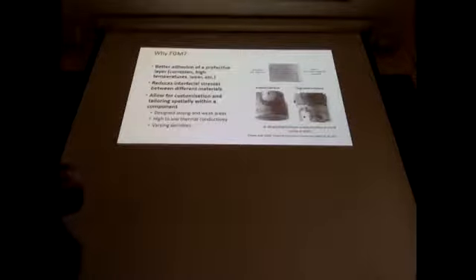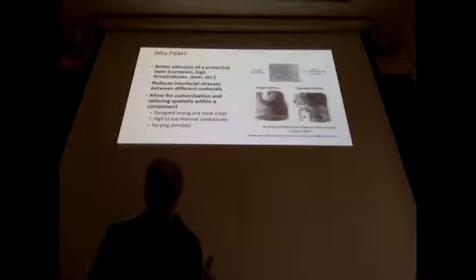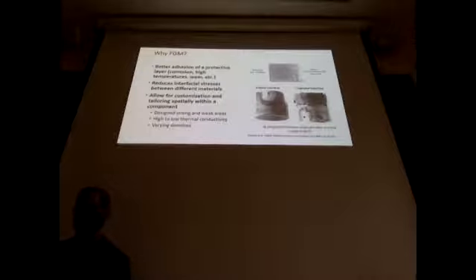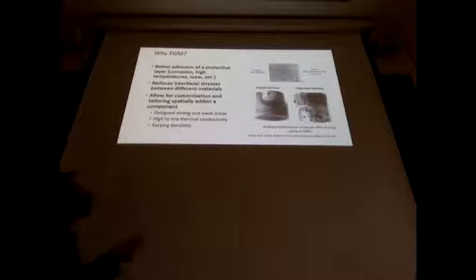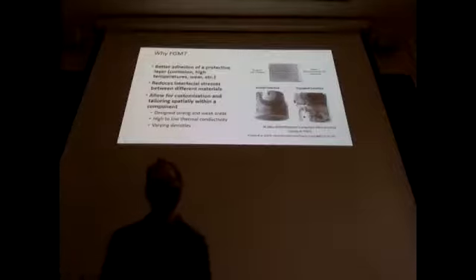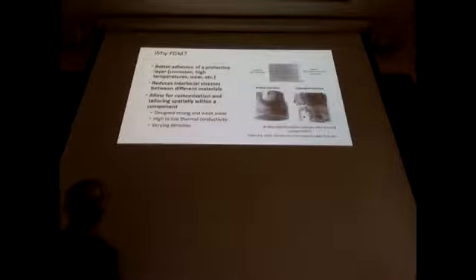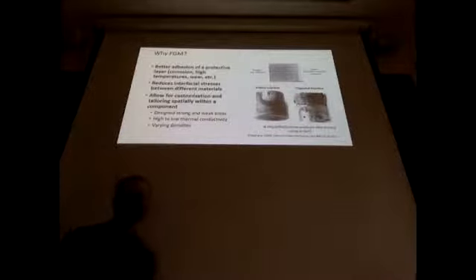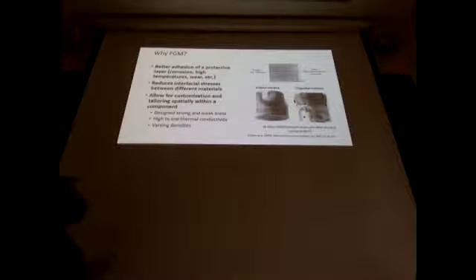So why functionally graded materials? It really comes down to trying to minimize the differences between the two materials that you're trying to adhere. You can just do it like a cladding, where you take a material and directly deposit it onto another material for, say, corrosion resistance. But that cladding has a weakness, which is at the interface. So the idea with the functionally graded is you can take that interface and extend it out. That hopefully allows better adhesion, and that cladding layer, that protective layer, can stay on your part longer. It also should help reduce interfacial stresses, especially if your component goes through cycling.